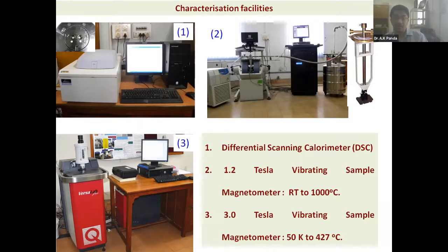We can vary the high field, 3 Tesla, from 50 Kelvin to 427. Of course, these are for characterization of your materials to find the entropy. And you can fairly go for the high temperature VSM also, up to 1000 degrees Celsius. I'm not going into details of it because it is possibly known to many others.